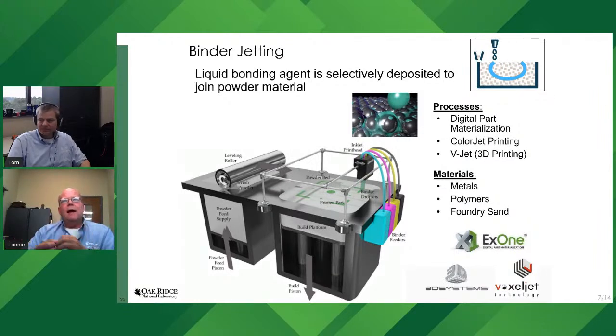You'll then put it in a furnace. You'll sinter it. Now it's going to be porous. So you take this powder, it's packed together, but it's not fully dense, because you haven't melted the material. So then you'll put it in a furnace. You'll sinter it together. It's now a porous structure. You'll then take a lower melt material like a bronze. The bronze is the typical that they'll do. And they'll put it in a furnace. The bronze will liquefy. They'll pull a vacuum, and it'll wick its way up through all the porosity.